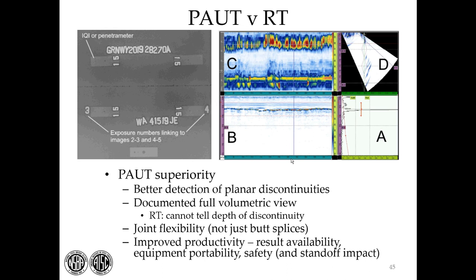Florida DOT did their own study and discovered that they got very good correlation between the code requirements of phased array UT and RT, and so now they allow it without engineer approval. The fabricator can simply choose to do it. And it really is better than RT, our workhorse method. First of all, it's better at detection of planar discontinuities.